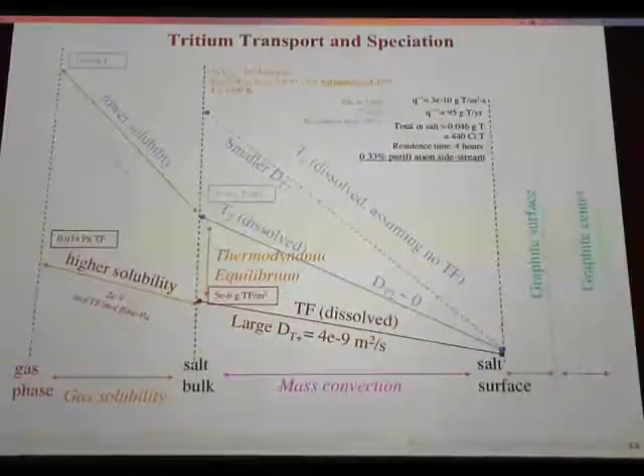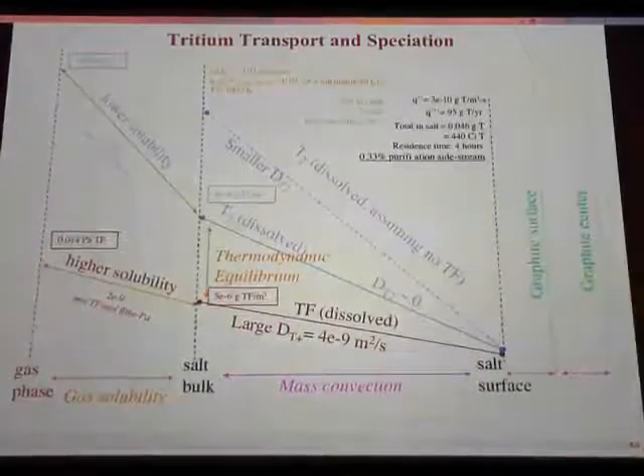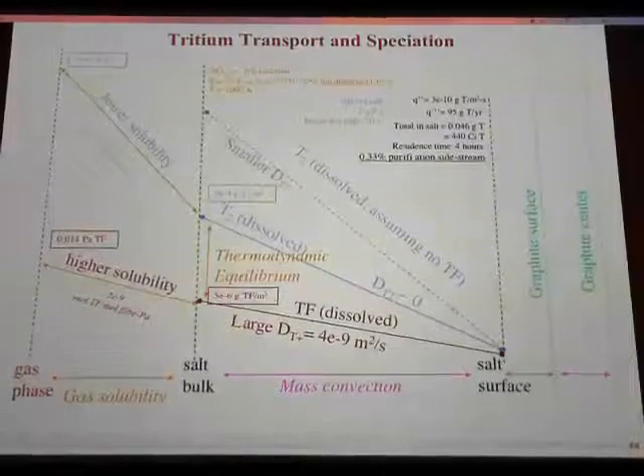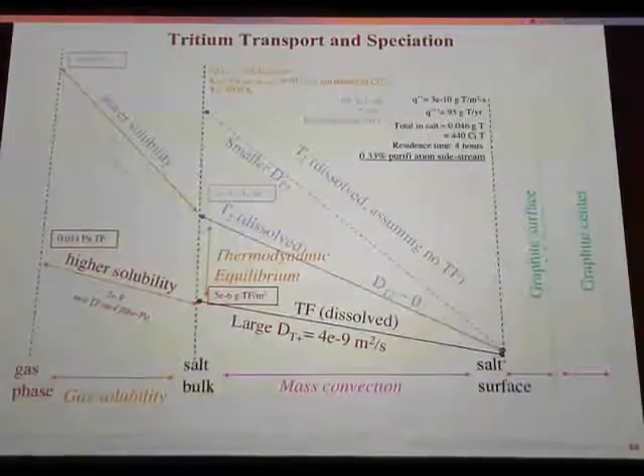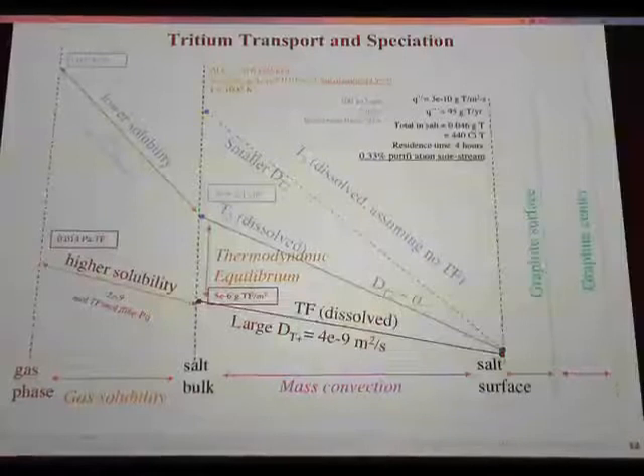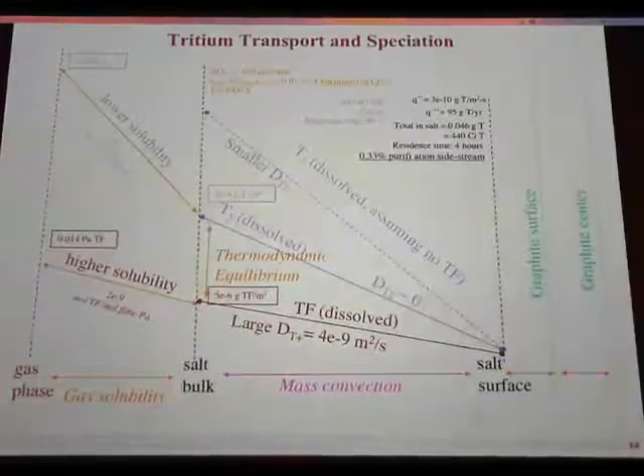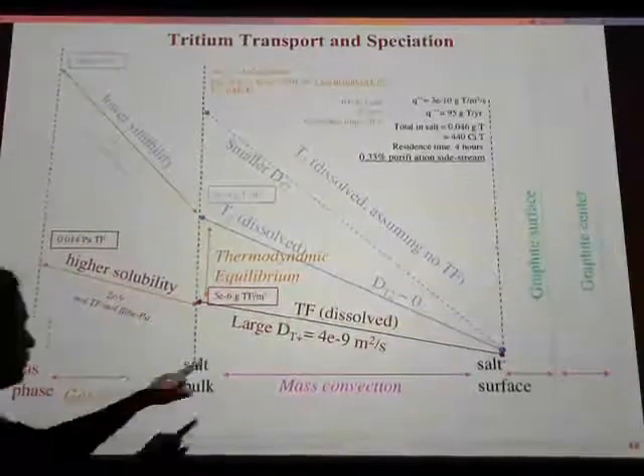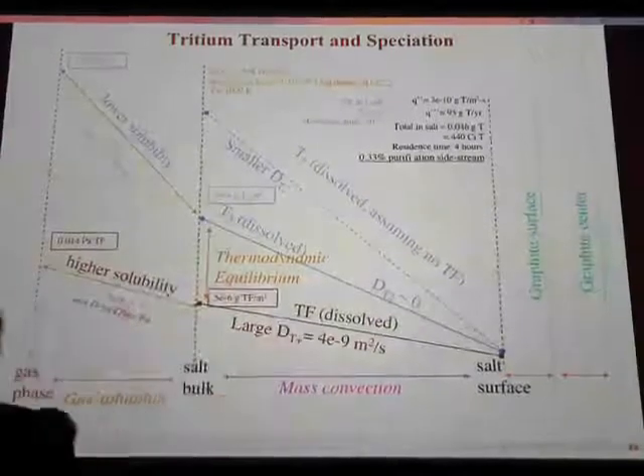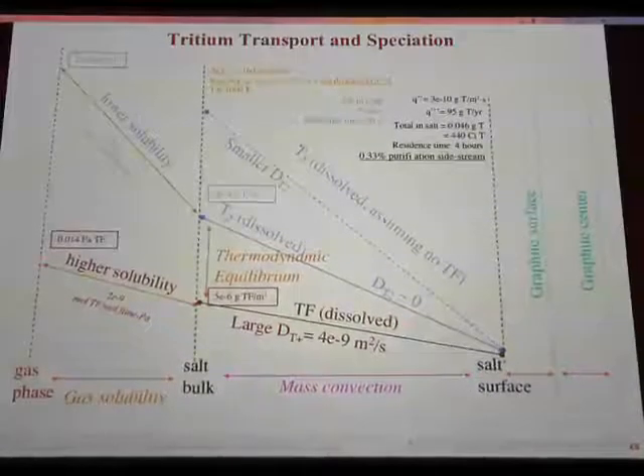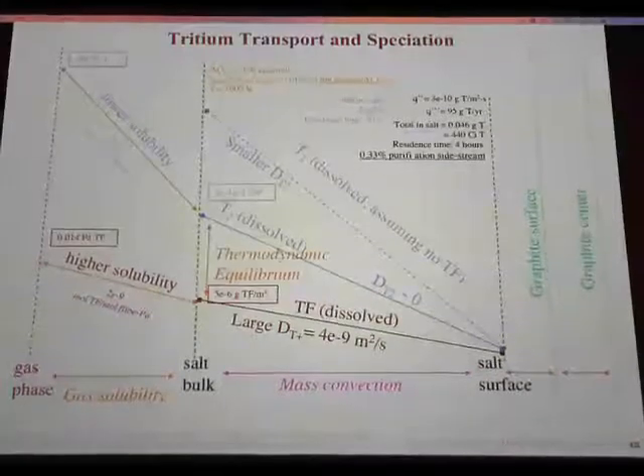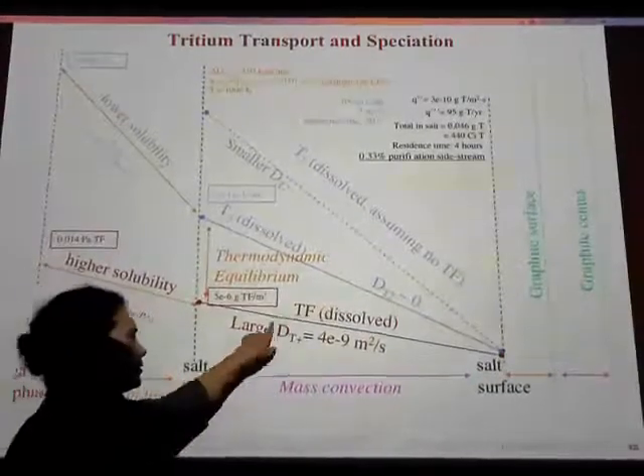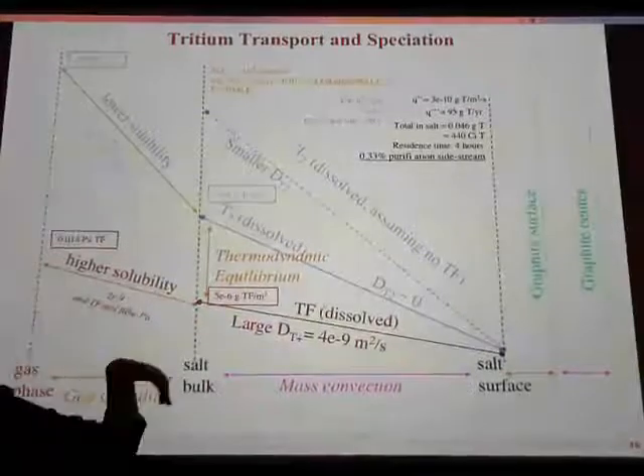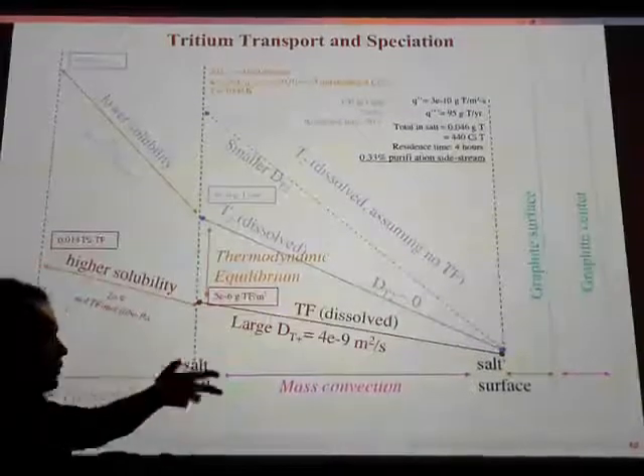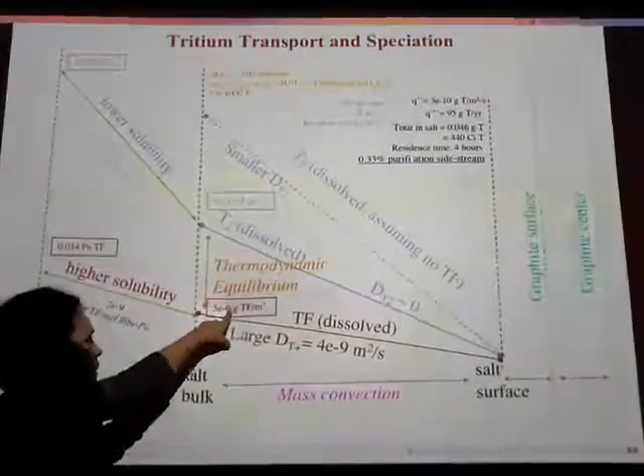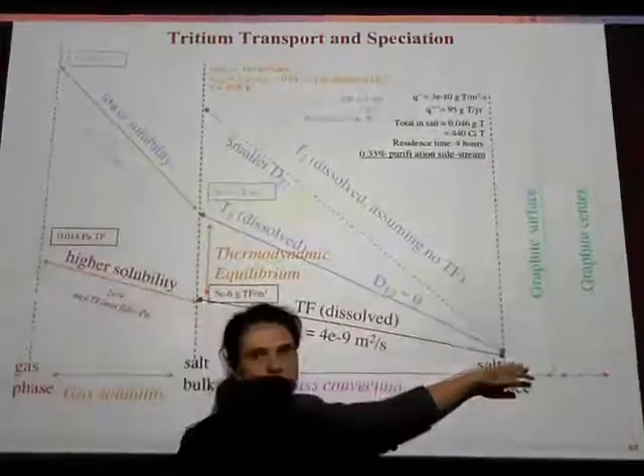And T2 won't have a very high diffusion coefficient in the salt. T plus will be the one that will diffuse quickly. And so if you compare the diffusion coefficient of T plus, for example, with the self-diffusion coefficient of F minus, you'll see that they're sort of comparable. And so that's an indication that it's probably T plus that's diffusing through your salt, not T2. And so what you need is this concentration, 10 to the negative 6, to drive the mass flux in.